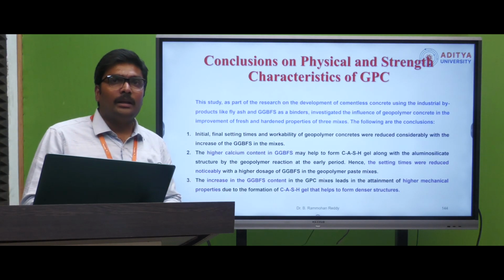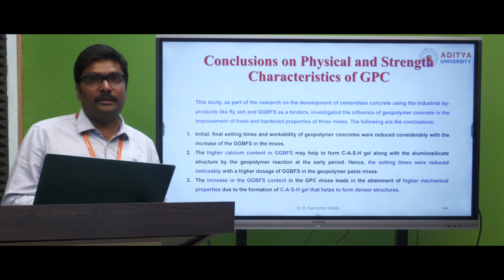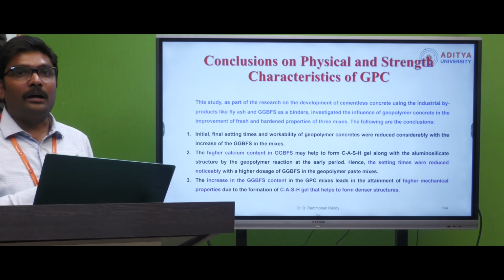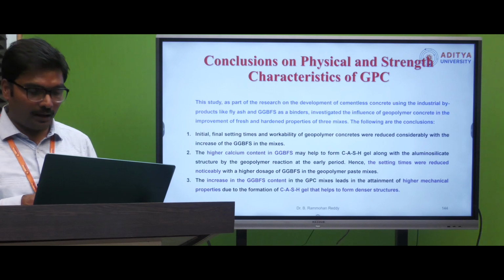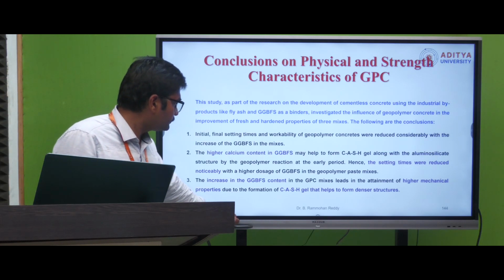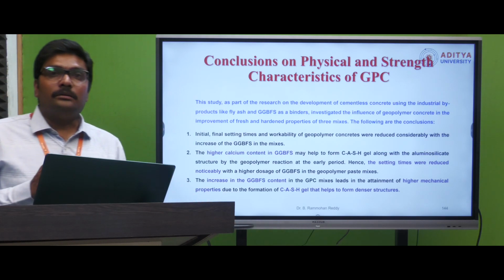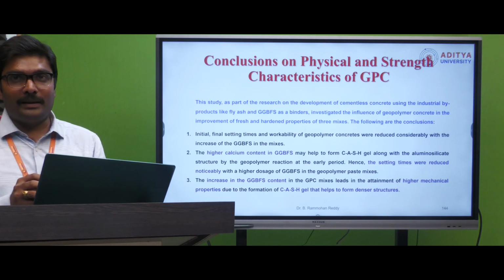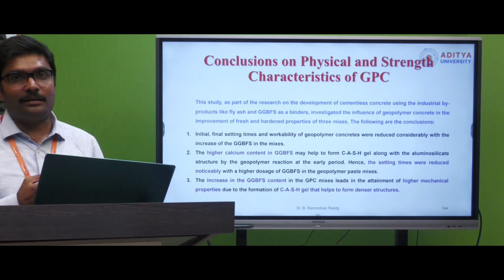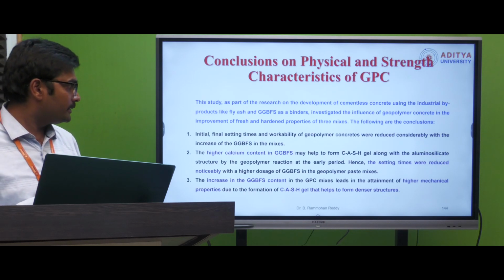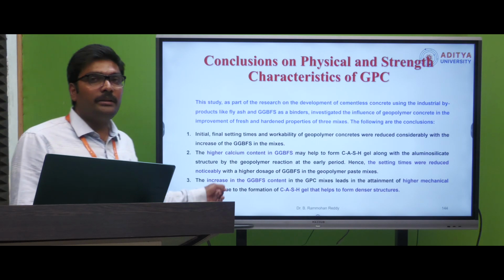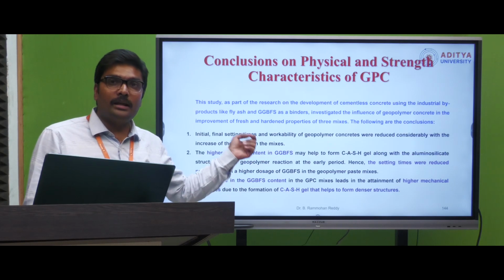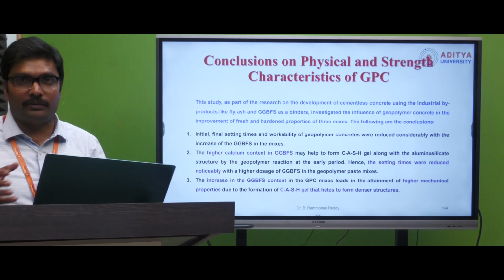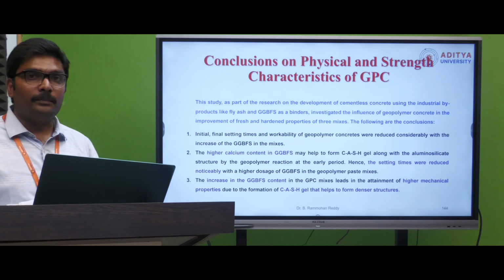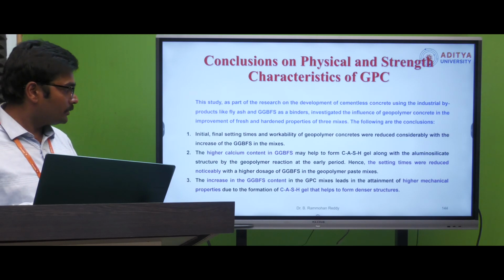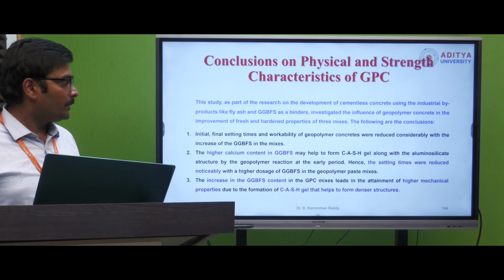And finally, from this lecture, and from the researchers who have evaluated geopolymer concrete, it's clear that replacing fly ash with GGBS will give better strength, durability and microstructural properties, where it plays a major role in the geopolymerization, and also using little quantities of GGBS will avoid the oven curing. We can go for sunlight curing or ambient curing. So that is another advantage for the geopolymer concrete.